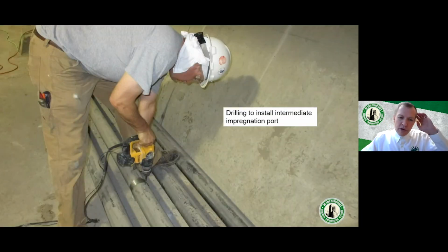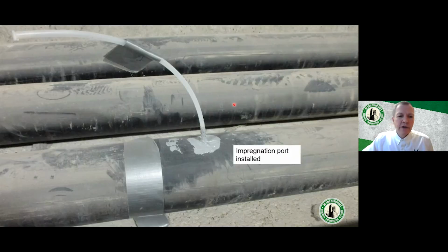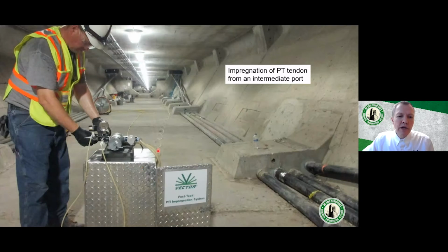So the previous 2 examples showed situations where the tendons were being impregnated from the end. This is one example I just wanted to show where intermediate ports were used. Here you can see the technician is drilling a port. So this is a 6 millimeter diameter or 1/4 inch diameter drilled hole. We're using special equipment so that it doesn't cause any damage to the strands. Here you can see one of the ports is installed into the duct, and here you can see the pump assembly, and it's pumping material from a reservoir here down this hose to an intermediate location, and from that location is pushing the material in both directions.